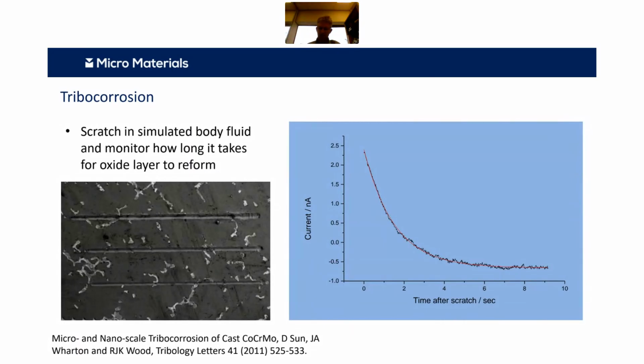Similarly, here is some work from quite a number of years ago at the National Centre for Advanced Tribology, NCATS, in the UK, down in Southampton. Here, Sun was doing some work, in this case looking at scratching in, again, simulated body fluid, and performing the scratches at sufficiently high load that she could remove the native oxide. There you see a couple of examples, and different load levels creating different scratches. And from one of those tests, you can see on the right that the passivation layer is removed. When it's removed, it releases these metal ions. This is one of the mechanisms. As part of this aseptic loosening, this metal ion release is considered to be one of the headaches to try and avoid and design alloys around to mitigate this problem in joint design.